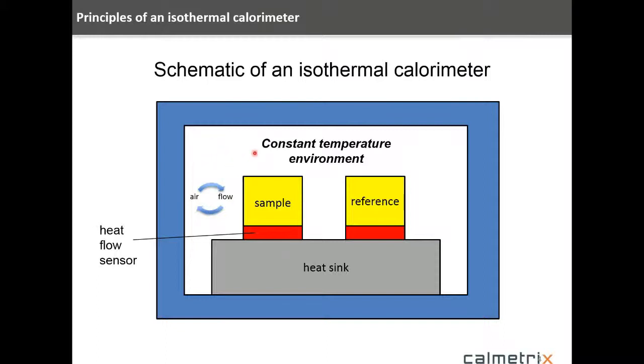So typically what we're doing is running this experiment in an isothermal mode. The sample tends to be pretty massive, 125 milliliters, with the types of materials we're dealing with. It may be in the order of tens of grams to hundreds of grams of sample. So the sample is pretty massive, and the actual calorimeter is massive. So temperature equilibrates slowly in these kinds of devices. So we typically run in an isothermal mode and look at the data as a function of time. So let's look at the sample and what might be happening in the sample.